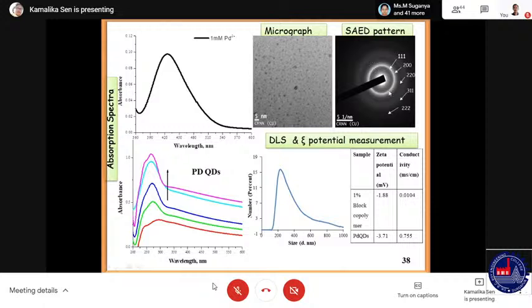These are the crystallinity showing SAED pattern, showing fine annular rings, and this is the dynamic light scattering and zeta potential results. DLS results show a higher size than the actual TEM dots. This is because of the hydrodynamic radius. This is the compatibility of the instrument.